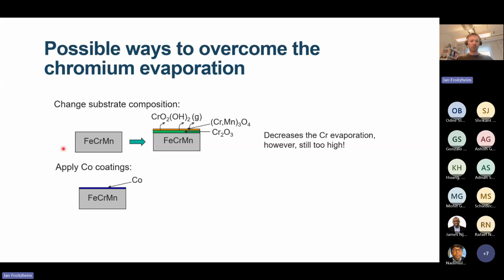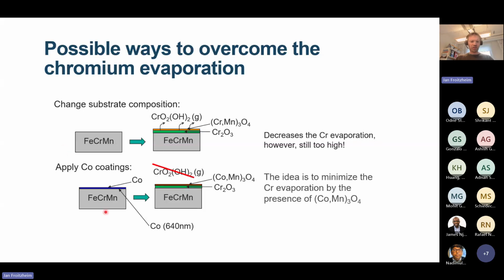That will give somewhat lower evaporation, but still too high. So what you can do is apply cobalt coatings, which is what we've been working on a lot. We use very thin cobalt coatings, about 640 nanometers. Then instead of the chromium manganese spinel, you get a cobalt manganese spinel. The idea is to block chrome evaporation with this cobalt manganese spinel.